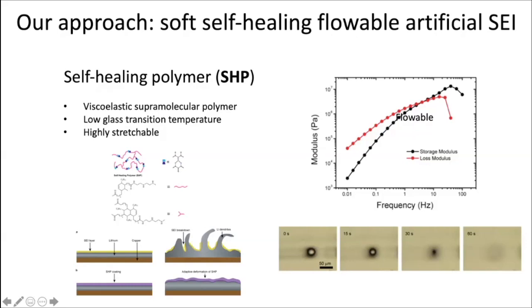So on the lithium metal side, we thought that the self-healing polymer could also be interesting to apply as a protecting coating for lithium metal because of its flowable property, which we characterized using rheology. And for this polymer, in the microscope image you see on the lower right side, basically we poke a hole in the polymer, and over 60 seconds, you can see the polymer already move around and flow over the hole and seal the hole. So we thought that this unique property of this kind of dynamic polymer could potentially seal any pinholes on the surface of lithium metal and prevent cracks in the layer, which result in dendrite growth.